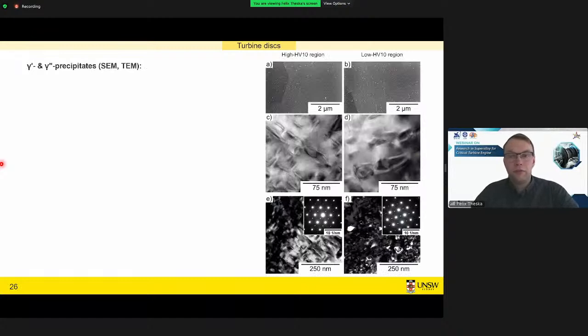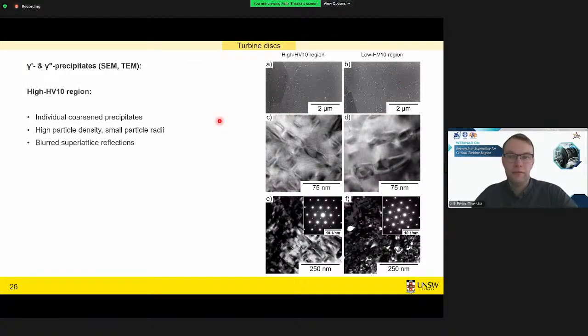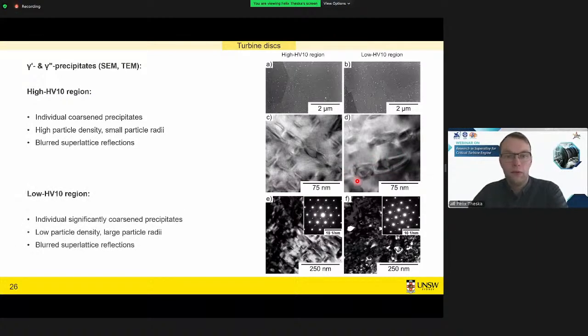If we now go to higher resolution techniques, we can use the SEM, set it up very carefully and find the precipitate structures, but it's easier with the TEM to find any differences, because we do see here in the bright field as well as in the dark field that there seems to be a lower density of these precipitates in the low hardness region, whereas the precipitates in the high hardness region are quite densely arranged.